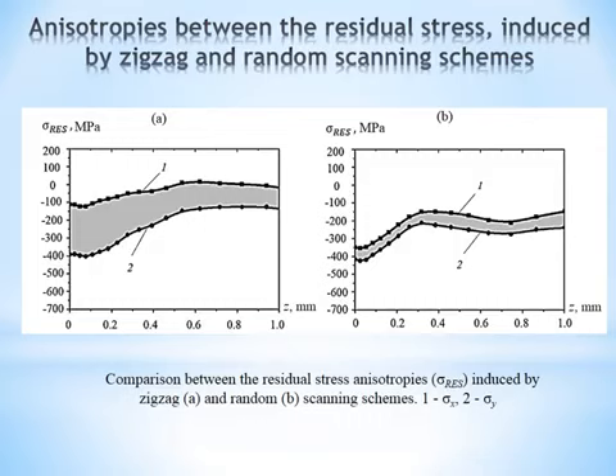The difference between zigzag and random scan schemes can be visualized more clearly if the changes in the residual stresses sigma x and sigma y are graphically represented, as in figure 5, showing both comparisons. As you can see, the difference between sigma x and sigma y, which is indicated in the figure in the grid after scanning according to a zigzag scheme, is much greater than after scanning according to a random scheme. This means that with a random scanning scheme, the anisotropy of residual stresses decreases by about 100 to 175 megapascals.